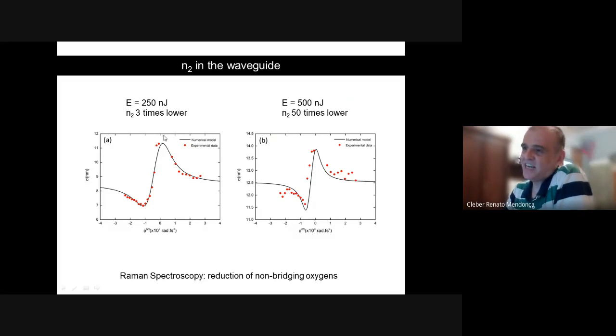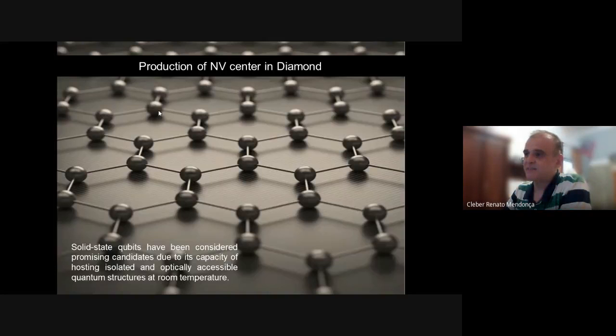So as we can see here, what we learned is that for waveguides fabricated with 250 nanojoules, the nonlinearity is 3 times smaller than the one for the glass itself. But of course, when you fabricate the waveguide with much higher energy per pulse, you get a nonlinearity much smaller. So indeed, we are decreasing the nonlinearity by femtosecond laser microfabrication, but we still have some nonlinearities, and maybe by controlling the energy used in the fabrication, you can get a nonlinearity which is usable for applications.